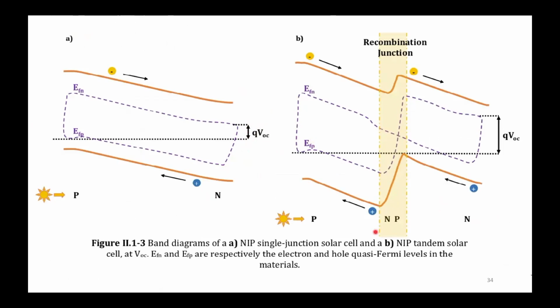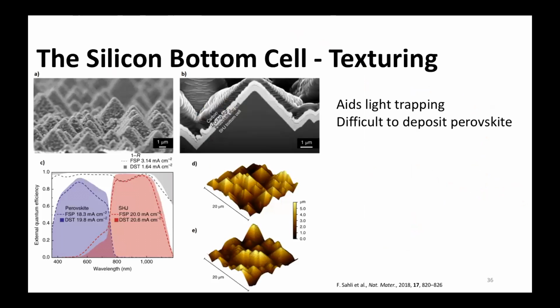So for these tandems, the situation is more complex. We have a charge here, we have a charge there, but also in the other cell. So this charge needs to recombine with that one in this recombination junction. Thereby, you can make a higher voltage. These charges have to recombine in this very, very thin layer. That's the idea. And by doing that, you can create a higher voltage. When you put two batteries on top of each other, they're in series. So that voltage is added.